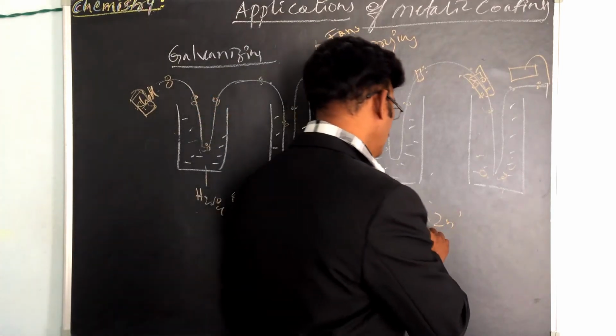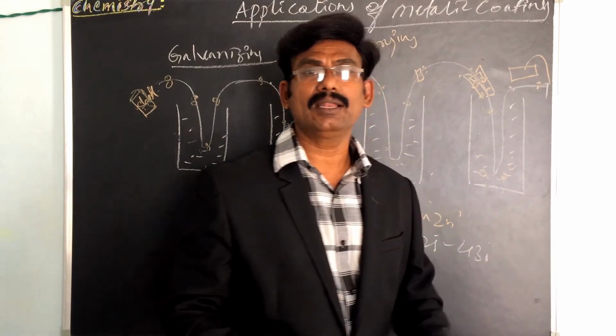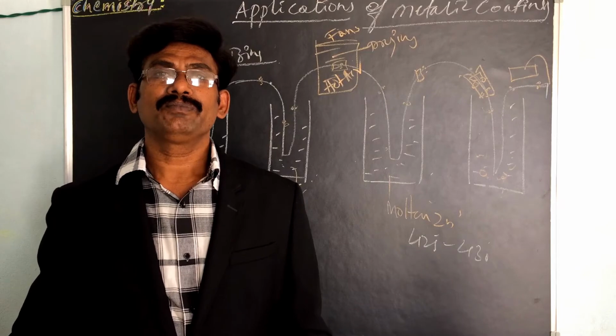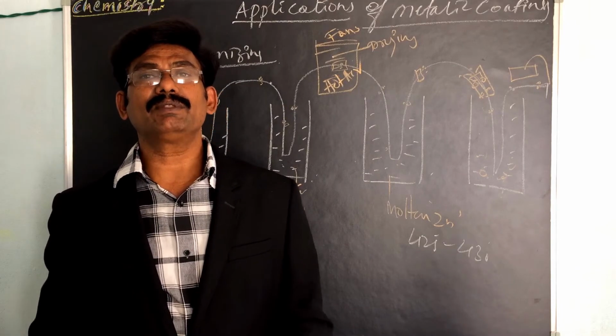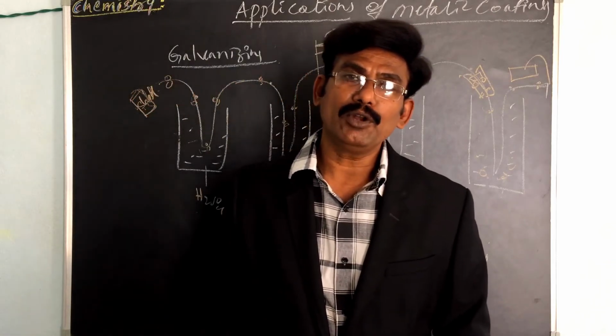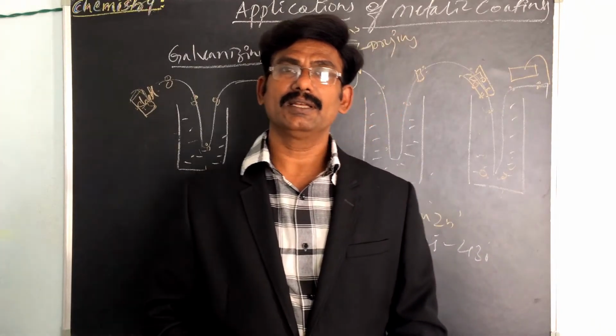It is 425 to 430 degrees centigrade. The surface of the metal bath is covered with ammonium chloride flux to prevent oxide formation.